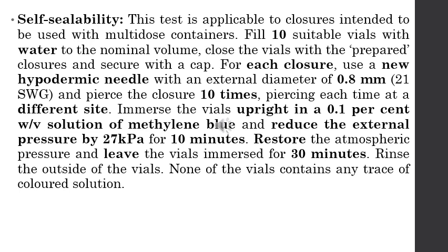After this, we have to rinse the vials and we have to check the vials for any trace of colored solution. So what happens is, if the rubber is not having self-sealing property, the colored methylene blue solution will enter in the vial and it will give color to the solution. So this is what we have to check. So if it is sealable, there will be no methylene blue inside the container.